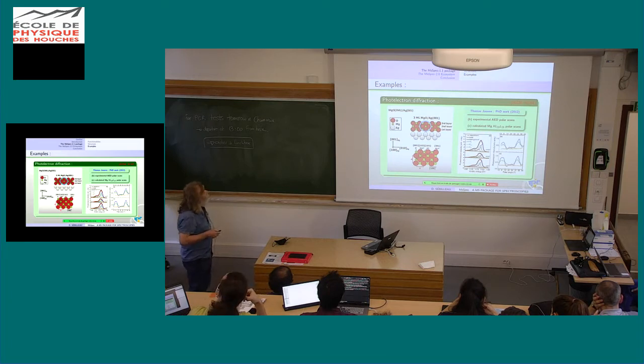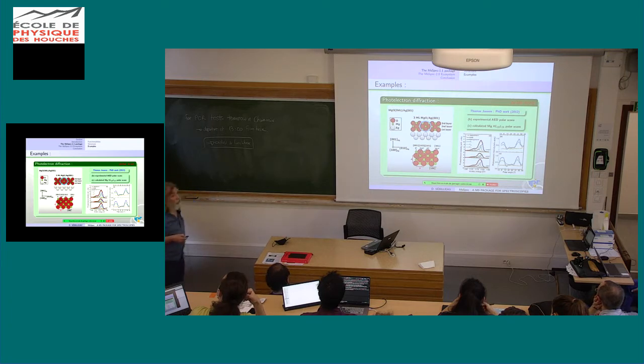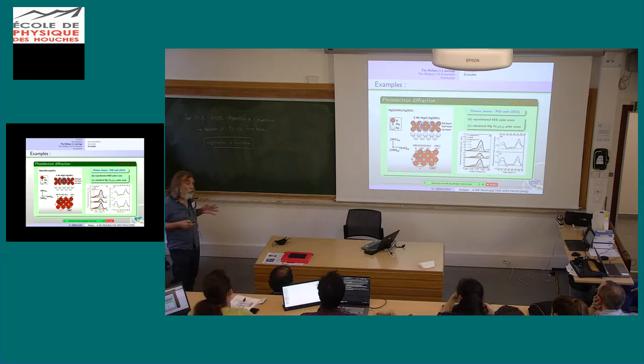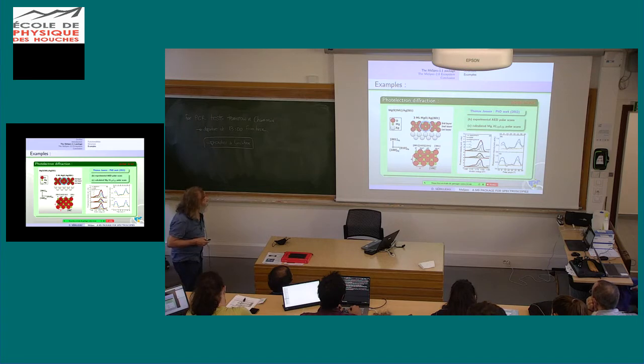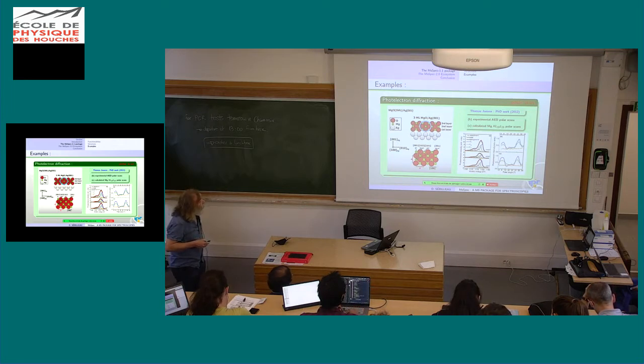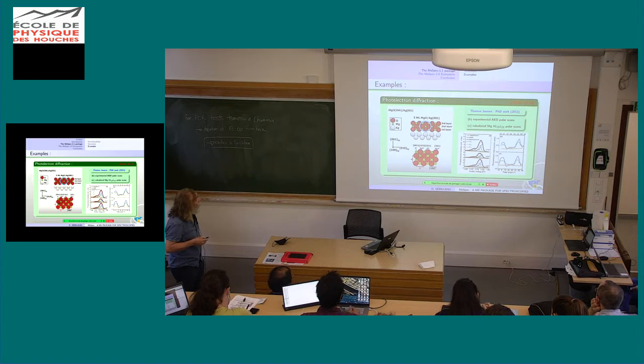For those of you familiar with core level photoemission, you know that there is a split in the peaks between the bulk and the surface — this is called the chemical shift. This helps you to discriminate between the two types of electrons. With three layers you can decompose your total photoemission core level peak into three contributions, each coming from a different layer. You decompose this peak for the different layers, which has been done in photoemission for about 40 years — the chemical shift was discovered in the 70s.